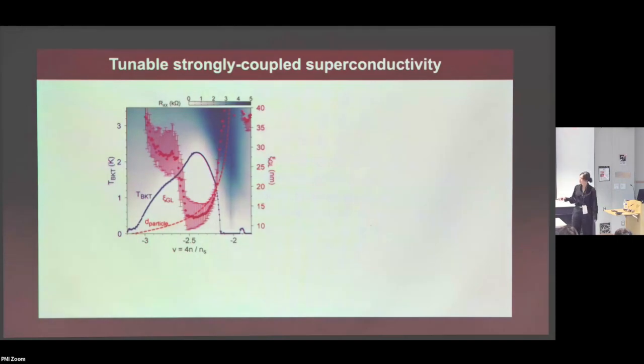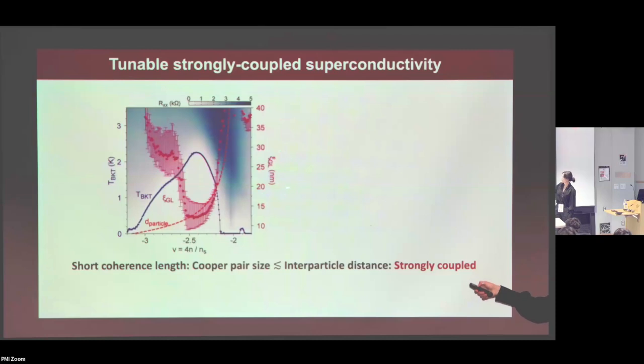And it doesn't just stop there. It turns out that it's not just the TC, but we can also control the strength of the superconducting pairing itself. For example, we can go to some high displacement field region and tune the superconductivity into this ultra strongly coupled regime. Here we have the superconducting coherence length as a function of doping density. You can see that this coherence length is of the same order as the average interparticle distance. That means your Cooper pair size is at most that interparticle distance, or even smaller, which is very different from the typical weakly coupled BCS superconductors, where the Cooper pairs are very large and far away from each other.